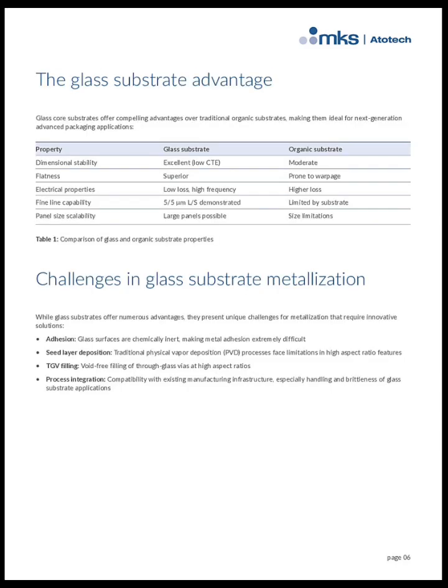Glass substrates offer clear advantages over organics, including superior dimensional stability, flatness, and electrical properties that support low loss and high frequency. They also enable fine-line capabilities down to 5 microns and support larger panel sizes. However, metallizing glass presents challenges. Adhesion is difficult due to the inert surface. Seed layer deposition struggles with high aspect ratio features. Through glass via filling must be void-free, and process integration requires careful handling due to glass brittleness. Addressing these is critical for successful manufacturing.